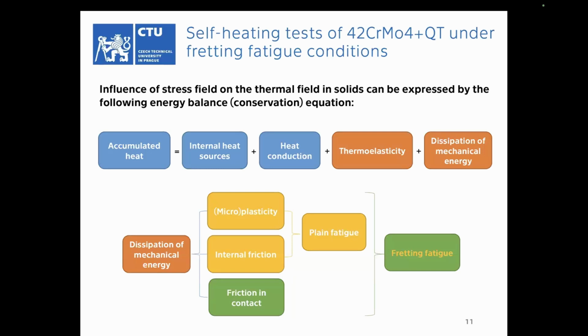So we have decided to apply some numerical procedure to compute heat and temperatures just for the friction in contact itself, to get the stabilized temperatures from this, and to subtract it from the temperatures measured, so that we obtain temperatures that are attributable to intrinsic friction and microplasticity in the material itself, without friction in contact.